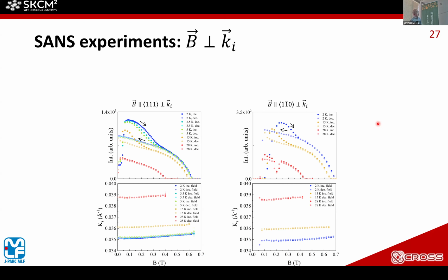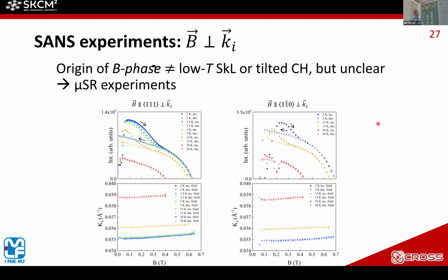At this moment, we are not sure what happens in this region, but these are some results. And from these SANS results, the origin of the B phase is not similar to the low temperature skyrmion lattice or tilted chiral helical magnet, but it's still unclear. Then we do the muSR experiment to understand the internal field distribution in each phase.